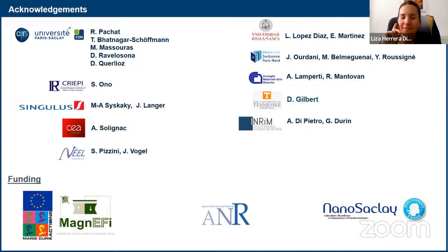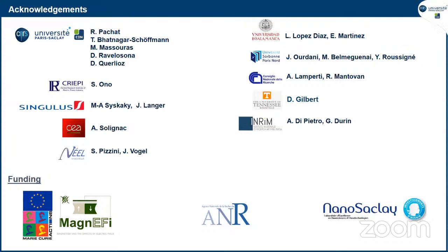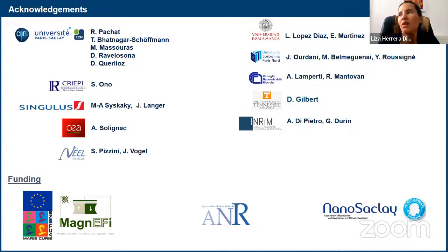So you just create a positive layer of ions without oxidation? Well, this is a little bit what is done in the case of charge effects. So then this was really the first measurement on the gating of magnetism. Actually, there was a really nice study, once again, from Institut, where they were using the ionic liquid. And as you say, the ionic liquid stops at the surface of your material. It doesn't go through. So then there, you just use it to create an electric field.